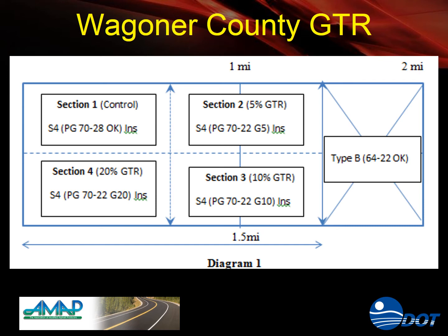We're looking at section 1, which is a PG 70-28, half-inch nominal maximum size. INS is insoluble, meaning it's a surface mix, so it's 2 inches on the surface. This is a little bit higher grade than what you'd use on a county road, but we want them all to fairly compare apples to apples. The next section is going to have 5% GTR. These are about 3/4 mile sections for a full transport load. And then this one's hopefully a 70-22 with 5% ground tire rubber. They probably start off modifying it with a 64-22, and it turns out to be what it is.